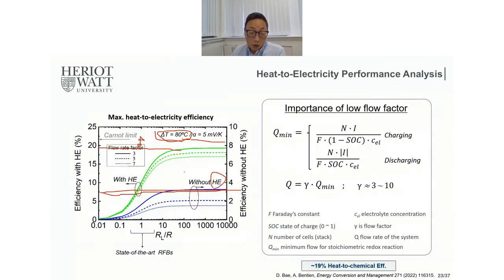And the other important and also interesting feature is that, depending on the flow rate factor, our achievable maximum efficiency varies significantly. So if the flow rate factor, shortly flow factor, increases, then of course the obtainable conversion efficiency significantly drops. Then let's see what factors we can change for making this system with a low flow factor. According to the well-known equation for the flow rate factor here, Q. I don't want to spend much of your time explaining this equation, but this gamma stands for the flow factor. Most flow cell batteries have a flow rate factor of 3 to 10.